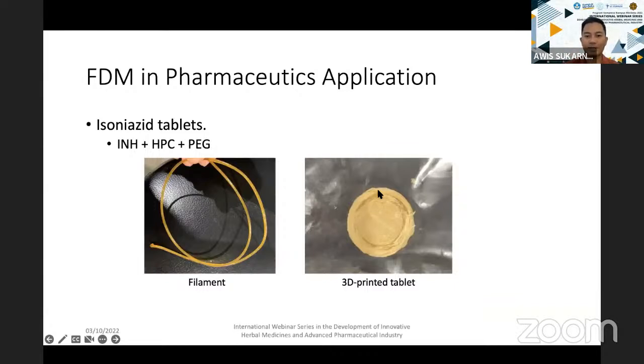And now there is a new one that she just printed, and at that point she got a lot better shape of 3D print. But here you can see it's quite rough. The one that she printed last week actually has a very good tablet shape. In this case, the HPC is the carrier, and the PEG acts as a plasticizer. Because HPC is very viscous, at first she just extruded the sample using isoniazid and HPC only, and at that point she found that some of the sample was quite hard.